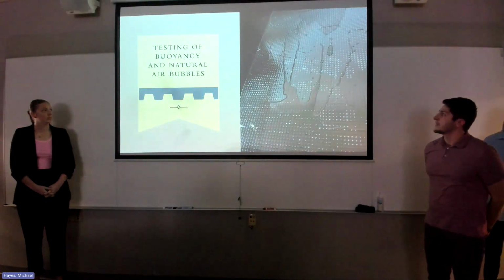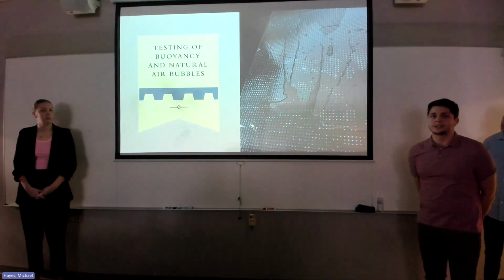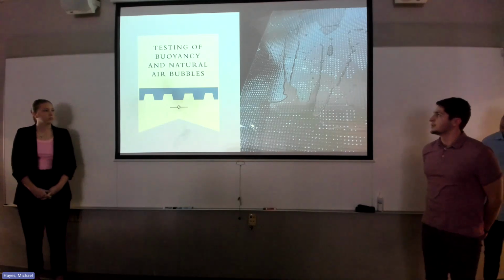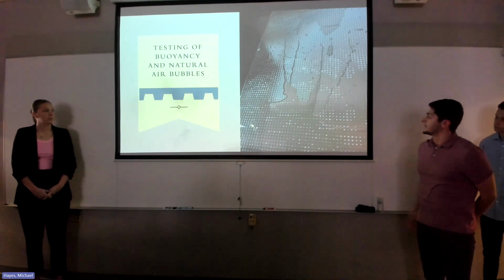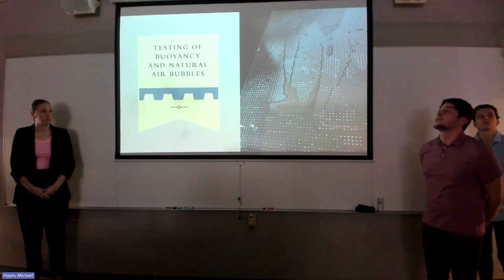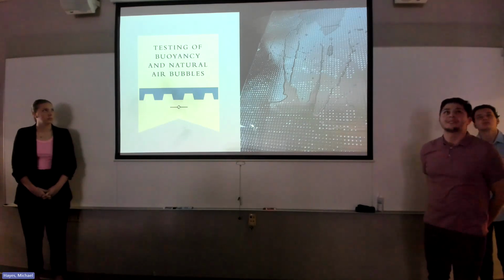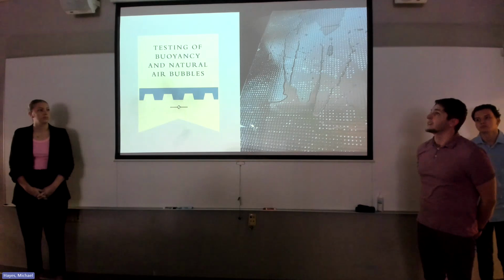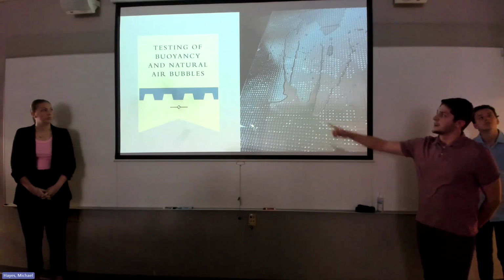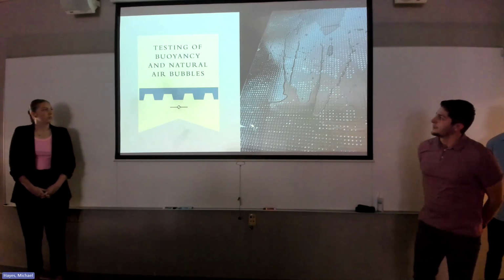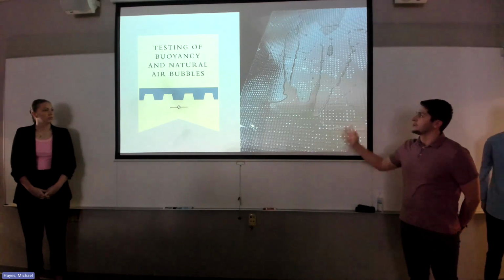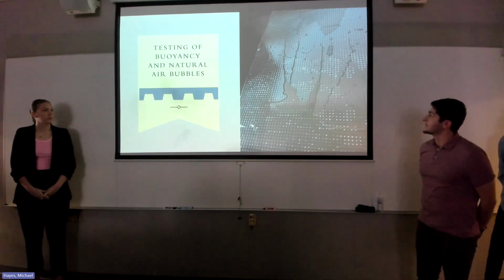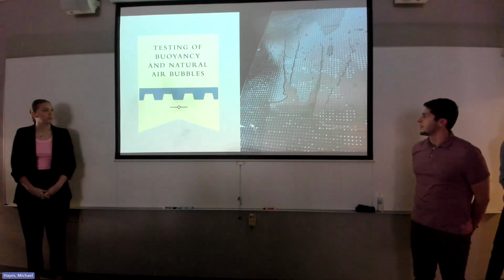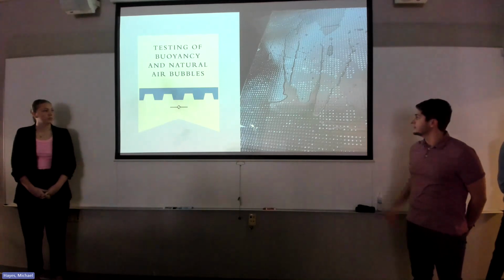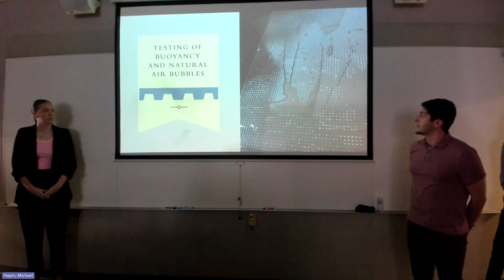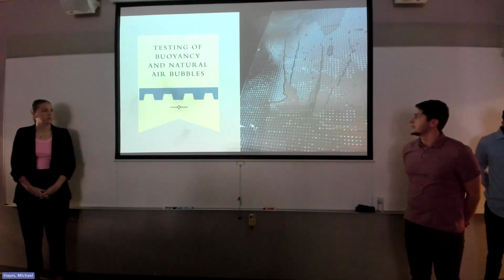To test, we wanted to see whether the bubble was actually critical for maintaining buoyancy on the pool itself. This right here is a material we found in the lab, which is similar to the ceiling covers used in classrooms. It has a design where there is an imprinted side and one side that is flat. We tested it in a tank of pool water to see whether air bubbles would help keep it buoyant. We found that it helps keep it buoyant and doesn't have any problems with staying above the water.